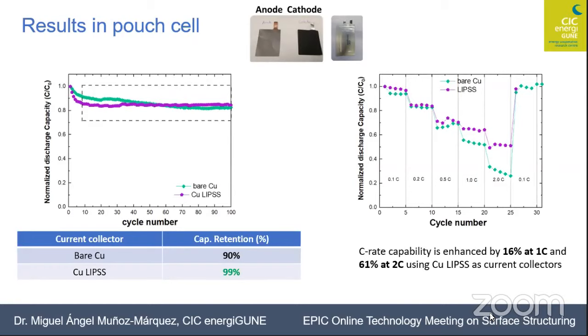We also notice that the capacity retention, this is the capacity that the battery can release compared with the initial capacity value, is 99% in the case of structured copper and 90% in the case of the conventional copper current collector. And finally, also a very interesting result that we obtained with this processing was testing how the capacity of the battery is affected when you charge or discharge at a very high speed. If you see on the right-hand side, 0.1C, 0.2C, 0.5C, this is the charge-discharge rate. 0.1C means charging or discharging in 10 hours, whereas 1C is charging or discharging in 1 hour, and 2C is in half an hour.